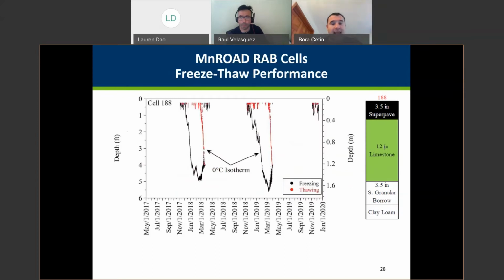Next slide, Ro. And here we draw these isotherms. Again, we assume 0 degrees Celsius: when the soil temperature goes below 0 degrees Celsius, we assume that it starts freezing. As you can see here, the freezing time can be determined. The black points show the freezing front and how it changes with depth, and the red lines show when the thawing starts and at what depth it starts. Again, it starts freezing at the top, and it takes some time for the freezing front to reach the bottom of the test sections. Then it starts thawing again at the top, and it takes some time for the thawing process to be completed all the way to the bottom of the test sections.